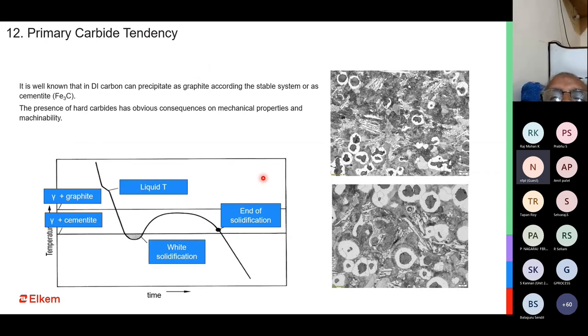Okay. I guess this is the last or probably the second last defect: primary carbide. Primary carbide tendency is something which is very common and very much of a worry for our foundries. We have a lot of carbide forming tendency in our casting, and why does it happen, especially in ductile iron? Because we have magnesium, and magnesium is a very strong carbide promoter. So although magnesium is a friend to us because we want it for nodularity, if present in excess, it can also be an enemy to us, because then it will form carbides, and it can give you shrinkage.